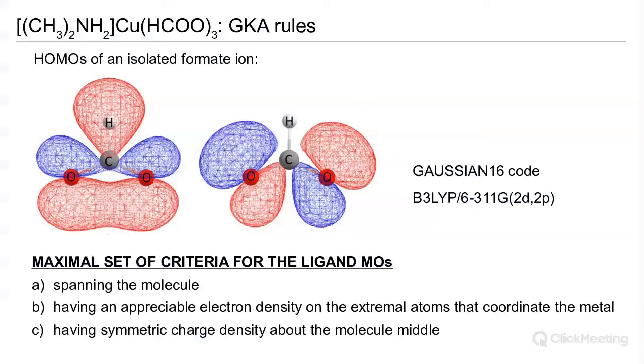So if we just take this one step further and think more generally about the GKA rules, then we proposed essentially a set of criteria for the ligand, such that it essentially emulates the role of oxygen in such a framework. And these were that the highest occupied molecular orbital that will mediate exchange must span the whole molecule. It must have an appreciable electron density on the extremal atoms that coordinate the metal, and it must be symmetric about the middle of the molecule.